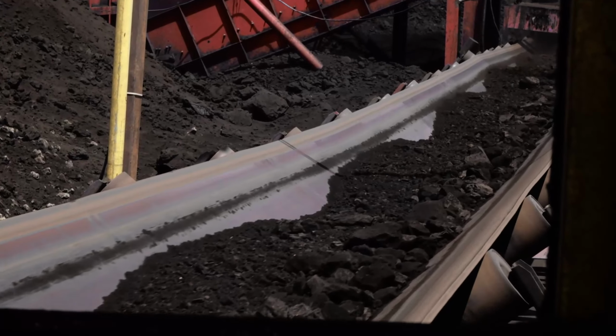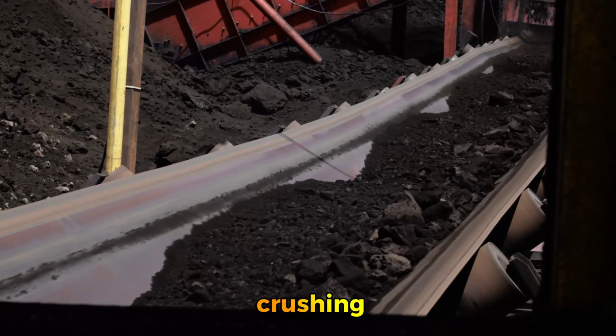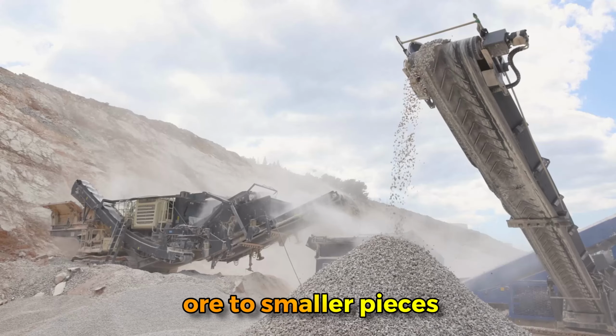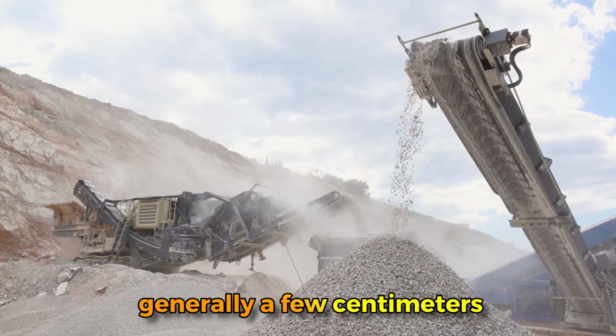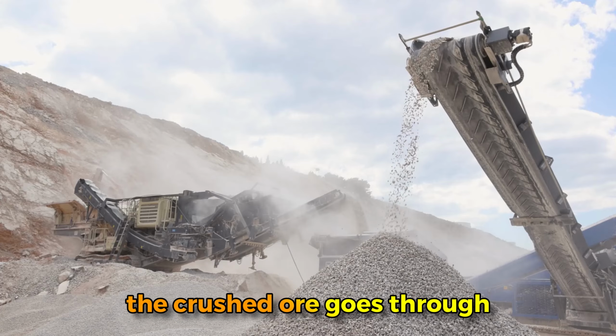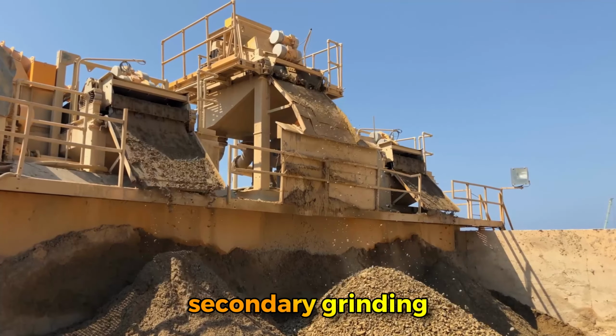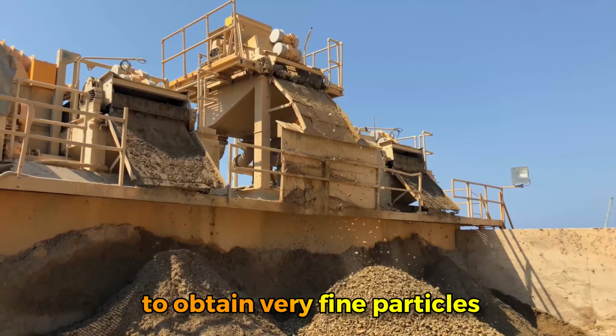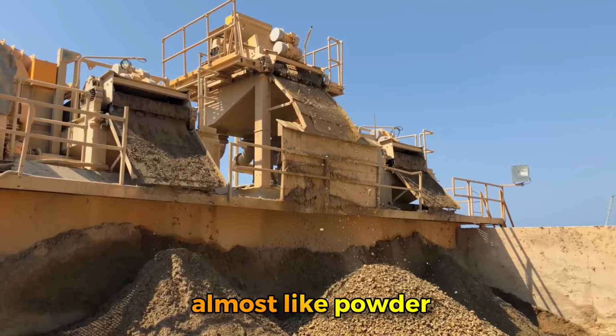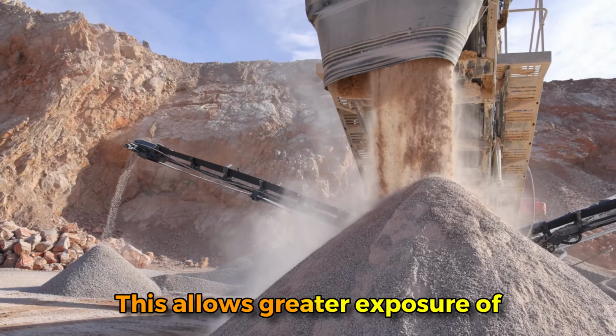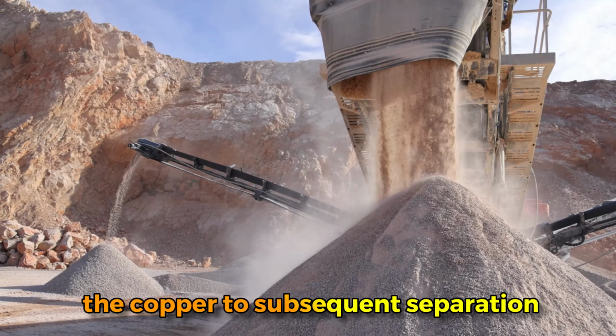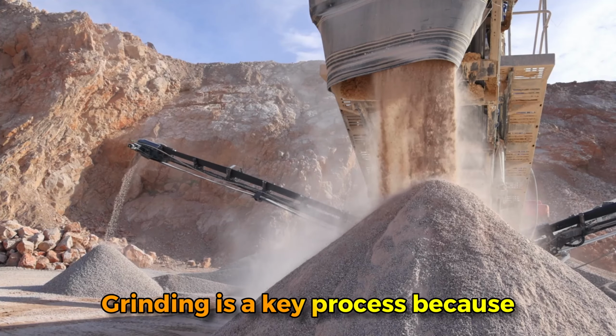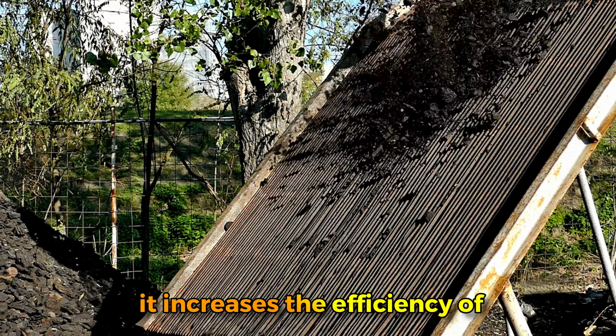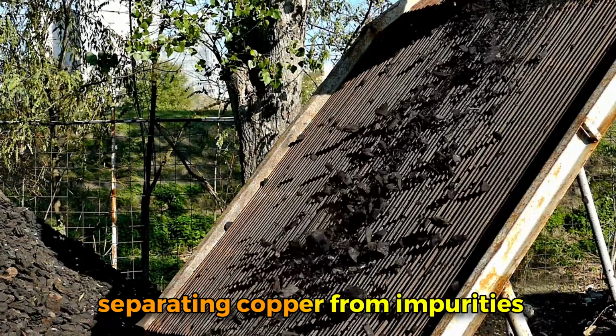The process begins with primary crushing, which reduces the size of the ore to smaller pieces, generally a few centimeters. Then, the crushed ore goes through secondary grinding, where it's reduced even further to obtain very fine particles, almost like powder. This allows greater exposure of the copper to subsequent separation processes. Grinding is a key process because it increases the efficiency of separating copper from impurities in the following stages.